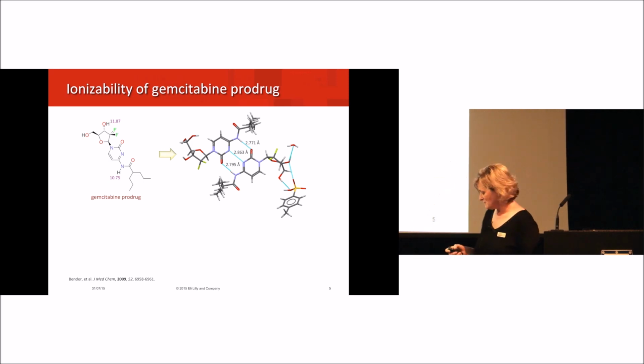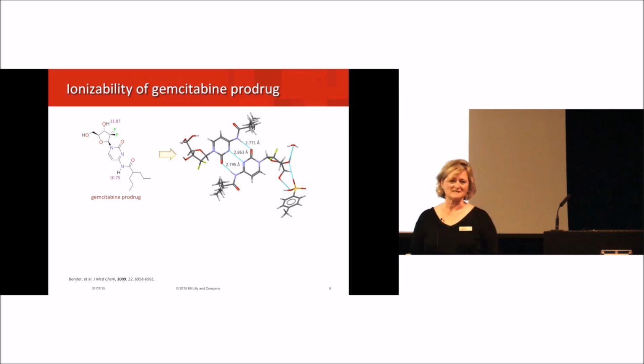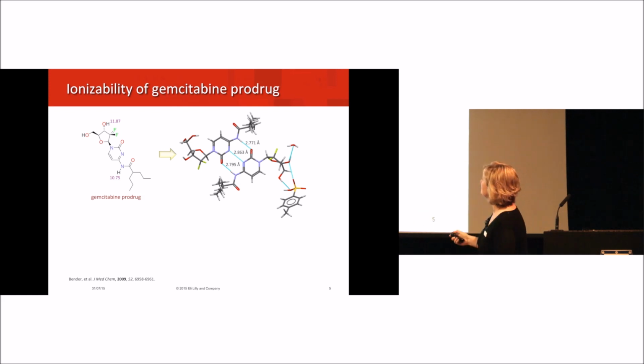Even though we were told that this molecule was not ionizable, of course you have protons in wrong positions, and this contact here is incredibly short, far shorter than what you find in the CSD between guanine and cytosine. So it really made no sense at all that this was, in fact, a co-crystal.